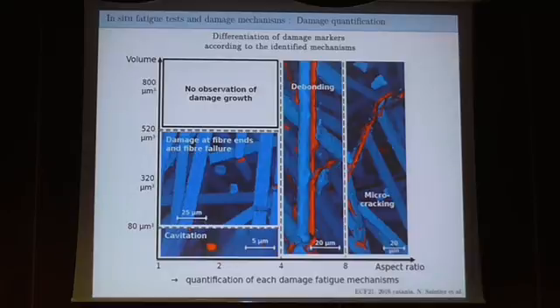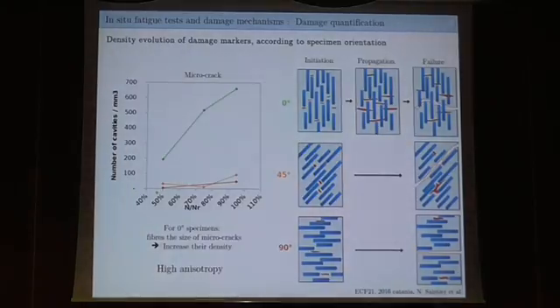So what we did is this differentiation of all the mechanisms depending on their shape, aspect ratio, or volume. So we could make a map of damage, and during this map you find the damage that I showed you before: fiber debonding, cavitation, decohesion, microcracking, and you can split all your 30,000 damage markers into individual markers and try to have some kinetics or evolution of each one of them. And that's what we did.